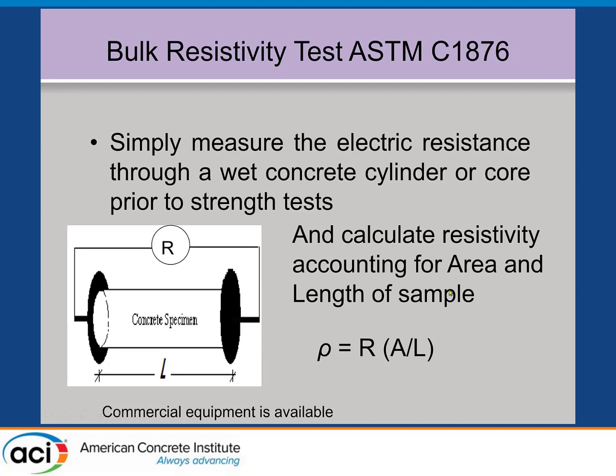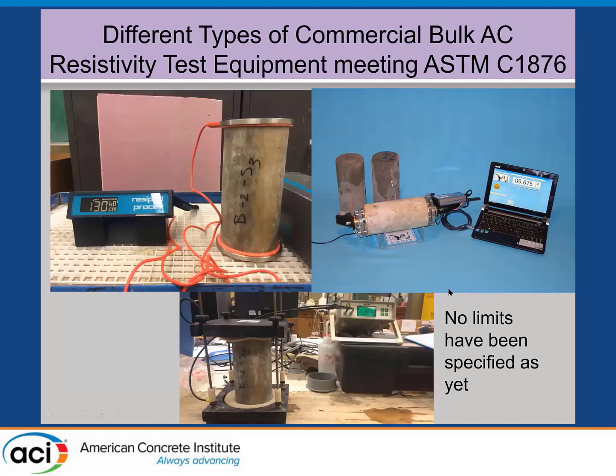So resistivity is a material property, and there's all kinds of commercial equipment. These are just three of them that I happen to have in my lab for measuring that meets C1876. Now we have this limit. Nobody's adopted it yet. We put it on the books so people can get used to it. We've done the same thing in the Canadian spec. In the Canadian spec, we expect the 2024 edition to have introduced limits for resistivity as a faster alternative to C1202. So instead of taking 6 hours to run the test, you can get a result in about a minute with these test methods.